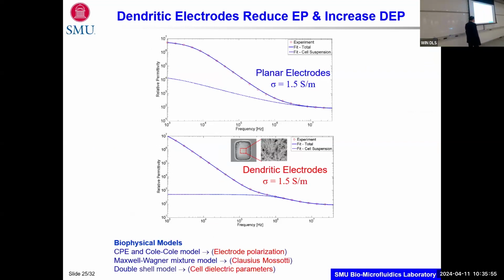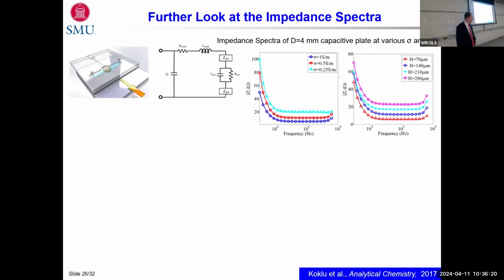So we did the same thing for that device that I showed the movie of with the micro valves. This time the valves are square. And as I alluded to in the previous slide, the planar electrodes did not work very well, but the dendritic electrodes did. So I can actually understand what's happening here, and that's related with dispersion. So the methodology worked extremely well. So the question here is, can we come up with something that will enable us to determine what to expect before we even build a device?